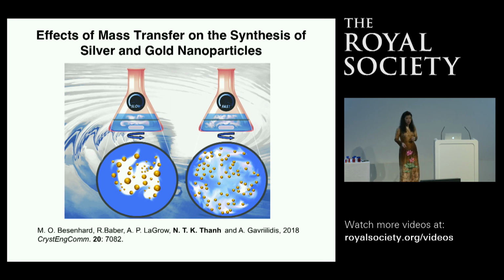So in collaboration with a colleague in chemical engineering, we could study this very classical reaction of gold and silver nanoparticles and study the effect of mass transfer during the synthesis. And it's something achievable in how you're going to start making the different products. I like cooking, and I did do experiments to make something right. And if you don't mix very well, then it gets lumpy and not smooth. So the same thing here: depending on the different speed of the mixing, you will have particles that are monodispersed or very polydispersed, that means very different sizes.